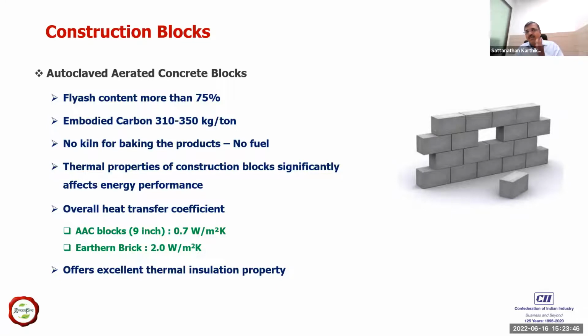Whereas if you take an AAC block, you use close to about 75% fly ash material and about 24% cement and then 1% aluminum powder for aerating it. And then there is no need for baking the brick. They mix all these materials, cut them into bricks, and then it is put in an oven where steam is supplied to take out the moisture.